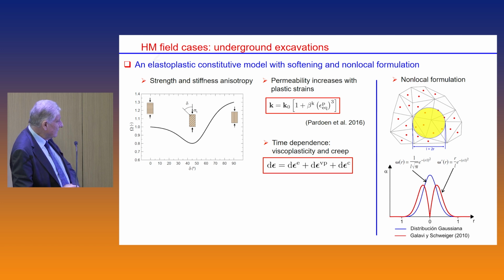There is a minimum around 45 degrees, a maximum when loaded parallel to the bedding. There is a variation of permeability with damage, well, to be precise, with plastic strains, and we take this cubic form that was introduced by the people at Liège, some time dependence, which is not going to figure today, and because we are into softening, we need some regularization technique, and what we use is a non-local formulation in which what happens in a Gauss point depends on what's happening in the Gauss points in the neighborhood, and this is the weighting function that we use, this red one, which is due to Galavi and Schweiger.